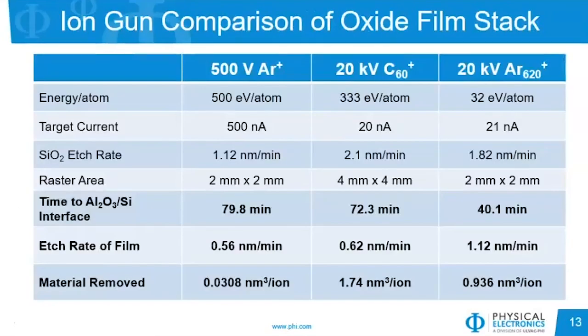Now this is a busy table, but what we're introducing here is an oxide stack. So we have 3 oxide layers on a substrate that I will show in just a minute, and we're looking at how they compare using these different ion guns for this analysis. The first column shows a 500 volt monoatomic argon that we'll be using. And just like the definition I mentioned in the previous slide, we have one atom with 500 volt beam voltage, so that has an energy per atom of 500 eV per atom.